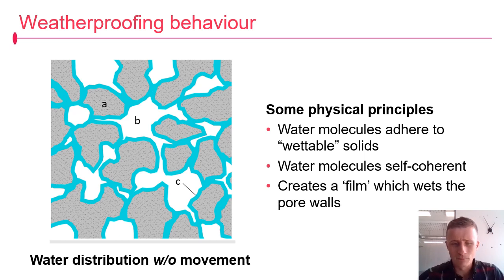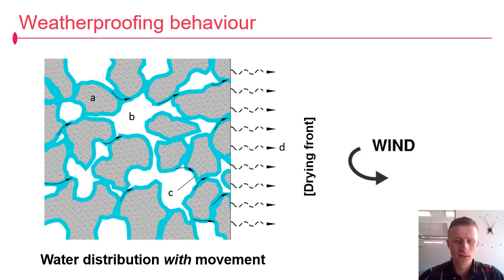The outworking of that is it creates a film across the pore walls. At high moisture contents, that's a thick film. At low moisture contents, it's a thin film, but it tries to stay interconnected. Introduce a drying front to this and watch what happens. So the principal driver behind the drying of wet stuff is wind blowing across the surface. Okay, so wind blowing across the surface physically removes water molecules from the front of the material.